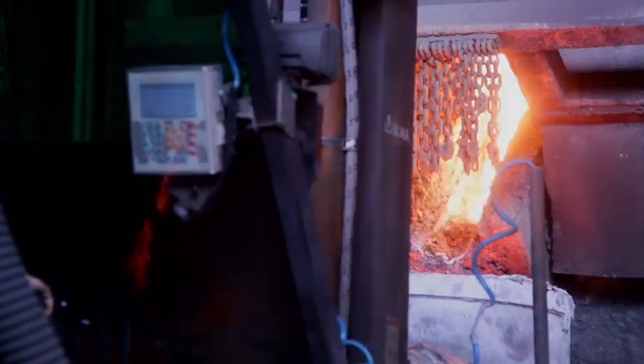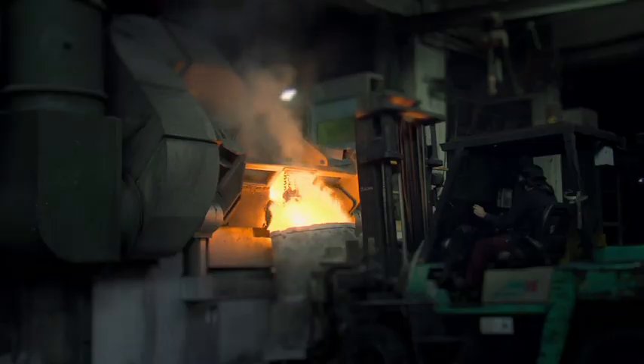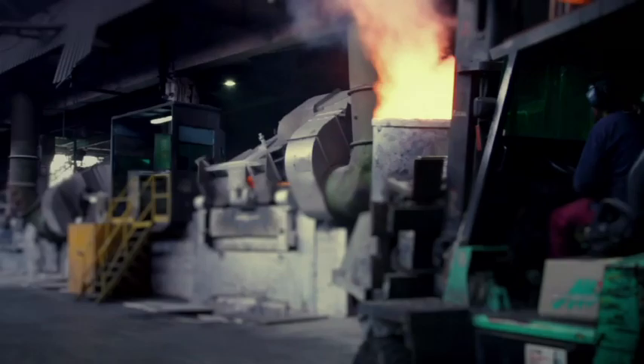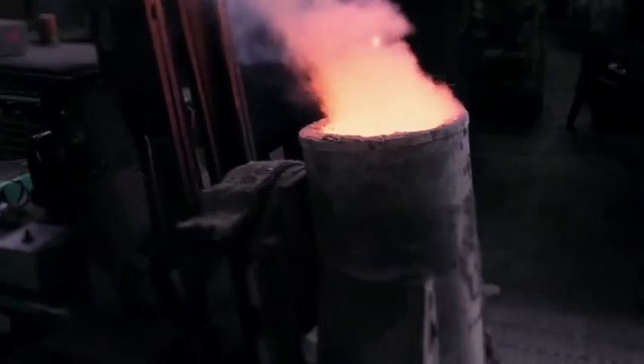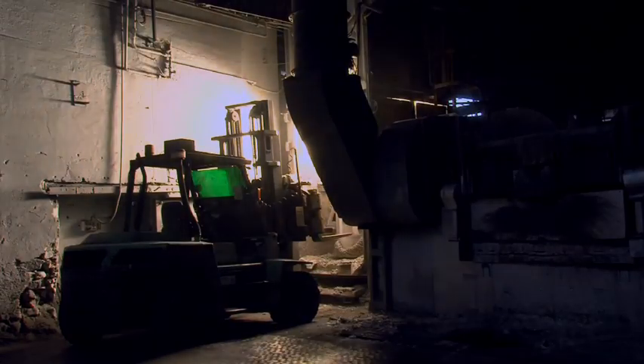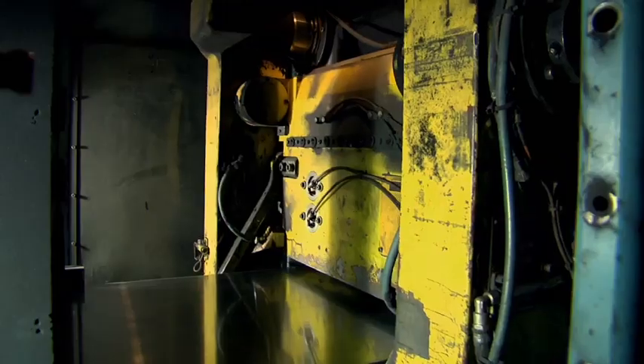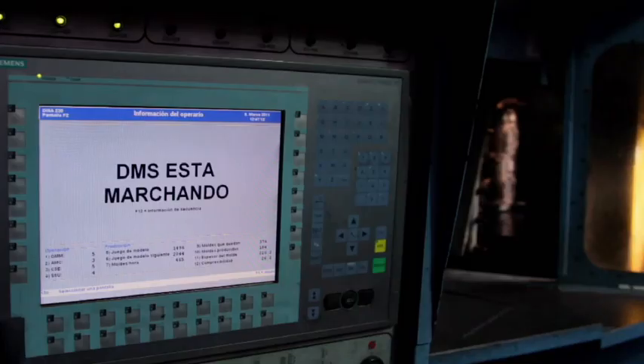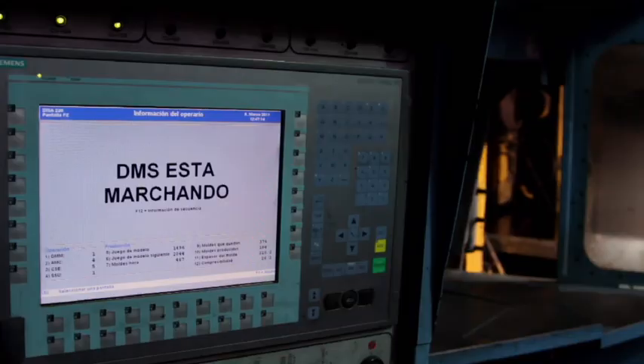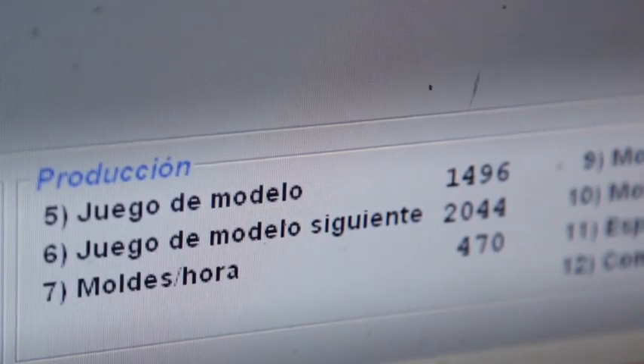Finally, 2,500 kilograms of molten iron are transported to the automatic casting section by forklift, magnesium treatment being performed along the way. The pattern tool or plate that lends the sand the shape of the part is fitted on the Disamatic vertical molding machine, and cores are added if necessary. The chemical composition, including magnesium, is controlled in the automatic casting holding furnace. The molds are filled at 1400 degrees C and the metal is poured in.